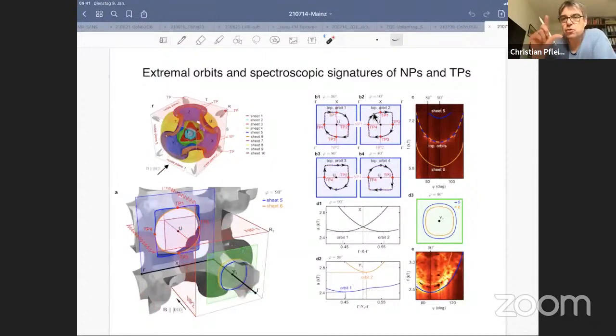And then we have two dominant frequencies in a particular part of the spectrum that we can very clearly assign, right? One of them is basically cutting across the nodal planes. It's not in plane with the nodal plane, but it's cutting across the nodal planes. And the other one is basically on the face where the nodal plane has been suppressed because the ferromagnetic moment is pointing in this direction. And this is summarized in these plots here. This is basically the section here, right? So we get 4 orbits, those intersecting orbits, right?